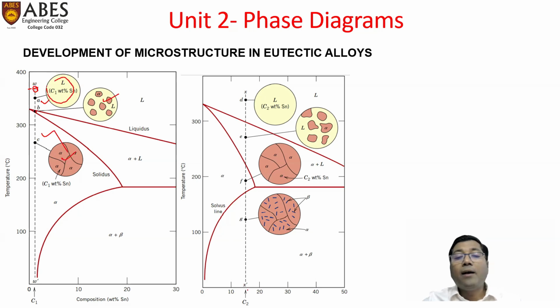Similarly, if we consider this C2 point, having a composition of 15% tin in lead, and we try to cool it from above 350 degrees Celsius, this D point, it is completely liquid solution, having C2 weight percent. Then at this E point, we'll have a combination of alpha, which is solidifying, and liquid. Then at this point, complete alpha would be present. And then when it goes below this temperature, due to limited solid solubility, it will again change into two phases, alpha plus beta. So here the microstructure would be alpha plus beta. How this microstructure changes at different temperatures gives the properties of the material at that temperature, what we discussed earlier.